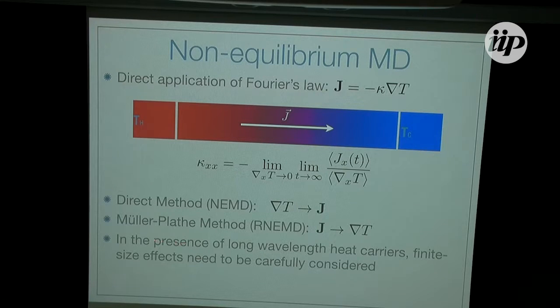Now the problem is that in the presence of these long wavelength phonons, or the heat carriers in this case, I have to be careful with the finite size effect. If this part here is smaller than the phonon mean free path, it means that the heat can travel from here to here without being scattered. I'm in the ballistic transport regime, essentially.